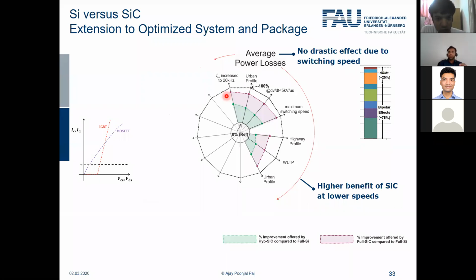But today, automotive traction inverters are mostly switching in this range of 10 kilohertz. And I have rarely seen someone switching much higher than that, maybe 12 kilohertz, but not 20, 30 or 40 kilohertz. Why? Because the higher the switching frequency, the higher will be the switching losses. And therefore, it does not bring much to the system. It only brings higher switching loss or lower efficiency. So most OEMs or manufacturers will not go for a higher switching frequency than, let's say, 12 or even maybe 15 kilohertz. And all are hard switched, right? Hard switched. Okay. Yes.